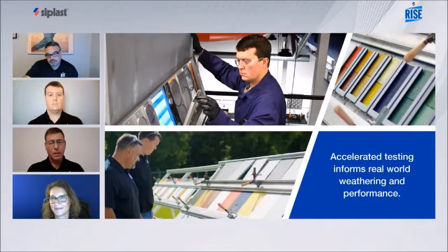So as Min was demonstrating the aging characteristics of PMMA, it's aged differently, and it's aged in a QUV oven, whereas liquid applieds do not have protection on the surface. SBS does, and so it's aged in a dry heat oven at 90 days at 70 degrees C or 45 days at 80 degrees C.